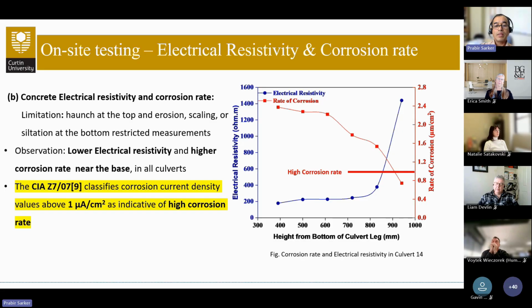At the bottom of the culvert leg, the corrosion activity was very high, and it was decreasing as we moved up towards the top of the culvert. The electrical resistivity shows just the opposite trend of the corrosion rate.